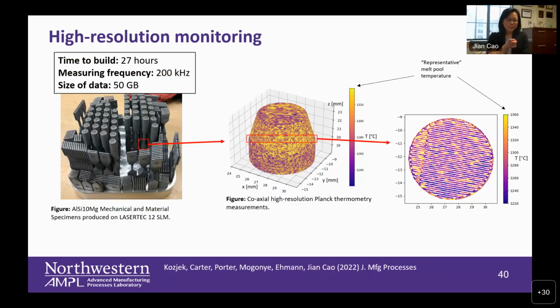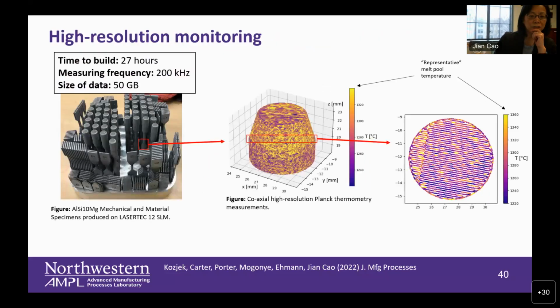Yeah. So for this particular one, these are measurements, not computational. But you train the neural net. That's right, to predict. We trained it, and it becomes really fast. The key thing, and we actually have a recent paper just accepted on this, is what we learned: to give you a better prediction, you need the previous 20, 30 layers of data altogether to predict the next one.